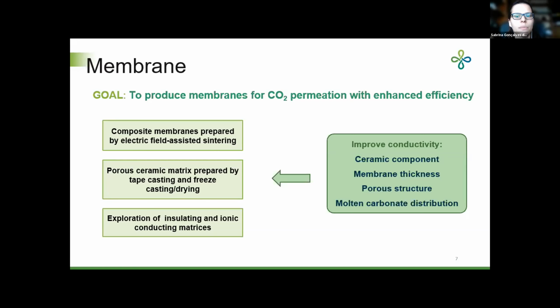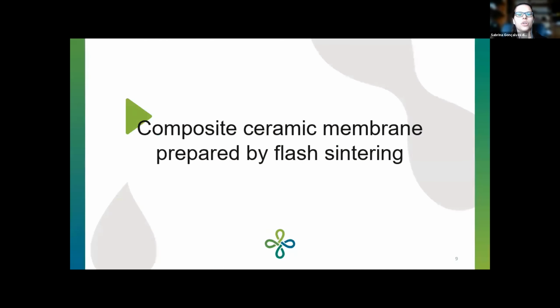And today I will present the main results that we have so far on composite membranes prepared by flash sintering and also the results obtained from the preparation of porous ceramic matrix using tape casting and freeze drying techniques, where we could decrease the thickness of the membrane and also change the pore structure. And we are also studying the use of insulating and ionic conductive matrices to investigate the conductivity of the molten carbonates. So first, I will present the results of composite ceramic membranes prepared by flash sintering.